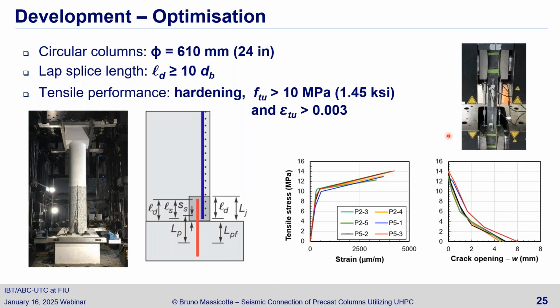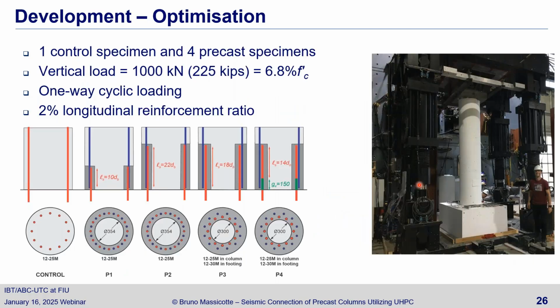And this is the type of behavior we get when we do direct tensile stress tests using the same test setup, or similar to that required by AASHTO now, or specified in AASHTO. This is the kind of behavior we get in the stress-strain domain, and that kind of behavior in the crack opening domain. So we got that and put that in place. We had a control specimen, and it took 4 specimens to tailor, to come to optimize the design, I should say. So this is the result. We're going to talk about this one.